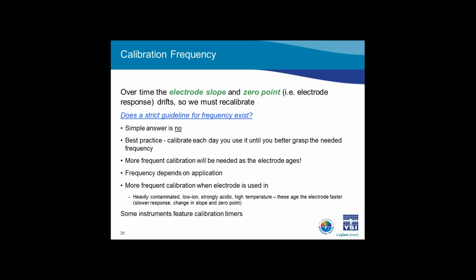This could be due to applications that may cause the sensor to drift faster, such as samples that are heavily contaminated, have low ionic strength, are strongly acidic, or when the electrodes are used in higher temperature samples. Additionally, some applications may require a higher accuracy or precision than others. In that case, the sensor should also be calibrated frequently.